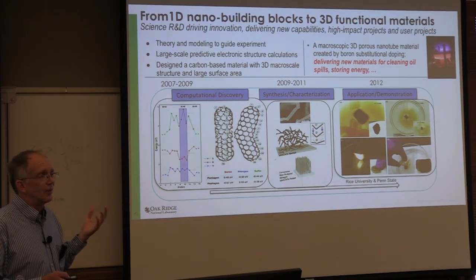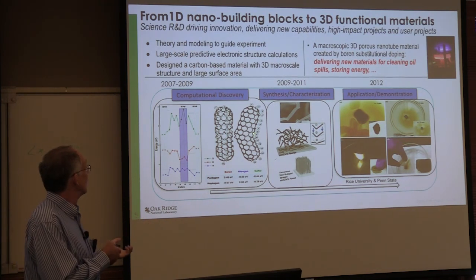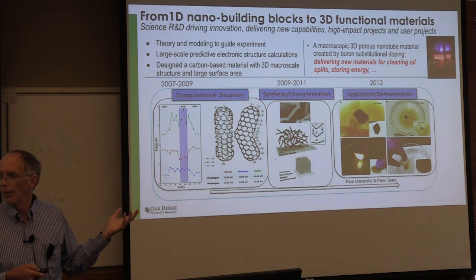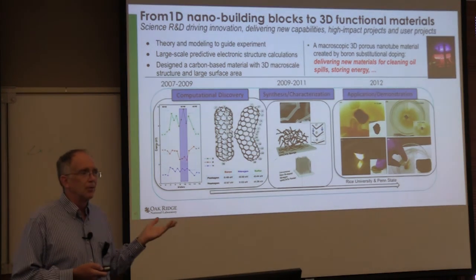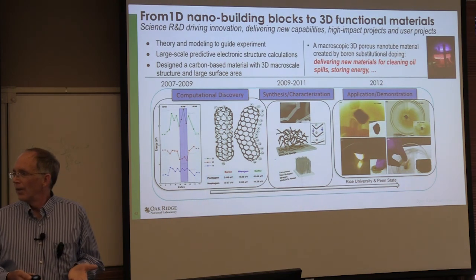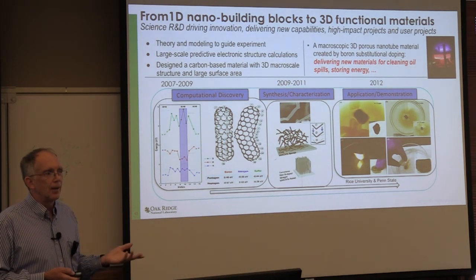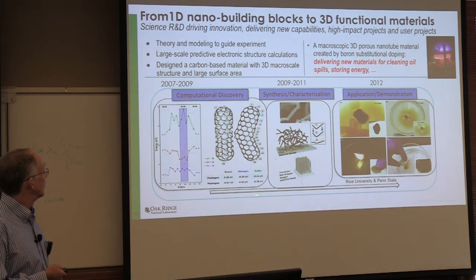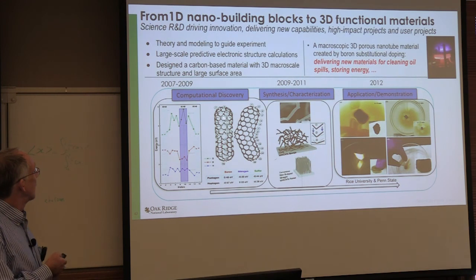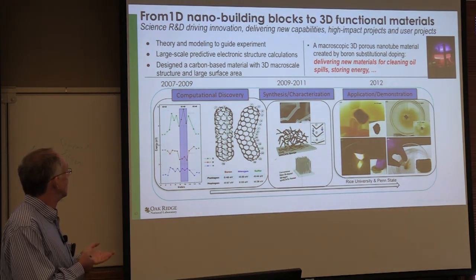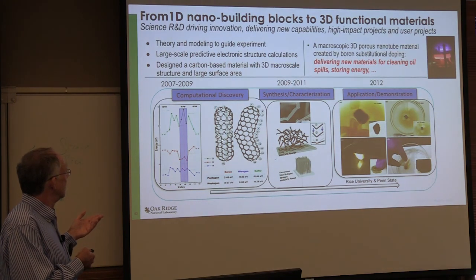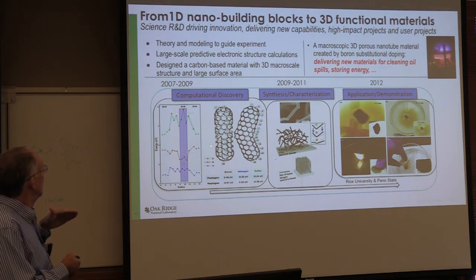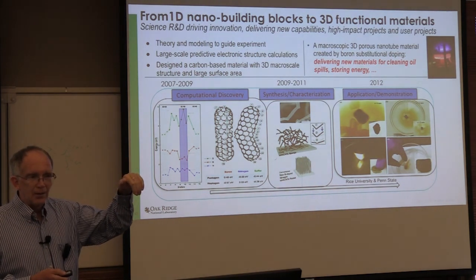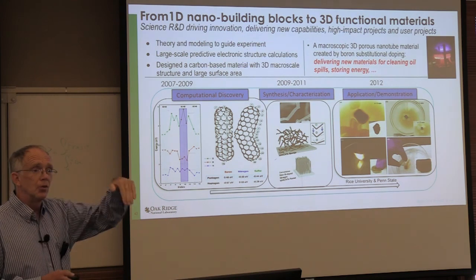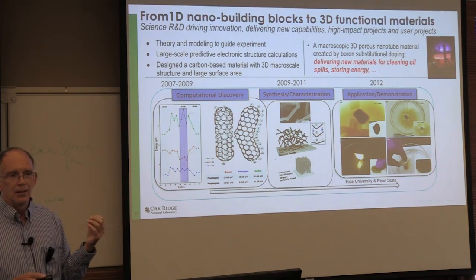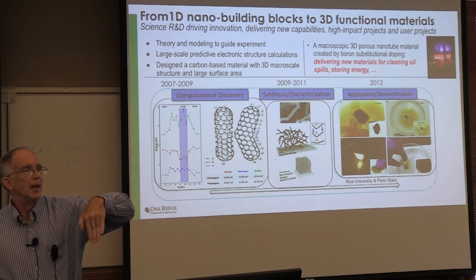So we said, we've got to use atoms that fit, right? If you put in something that's huge, it won't fit in the lattice, and it'll completely break up the network. The elements next to carbon, boron, sulfur, and nitrogen will fit in the lattice, and their atomic structure is similar to carbon. They're not that much different. So we rationally chose those and said, let's put them in this carbon nanotube and see what happens. What happens is certain elements like to sit in a zero curvature, flat position, certain ones like to fit in a positive Gaussian curvature, where it closes the tube, and certain ones like to sit in a negative curvature, where there's a turn made.